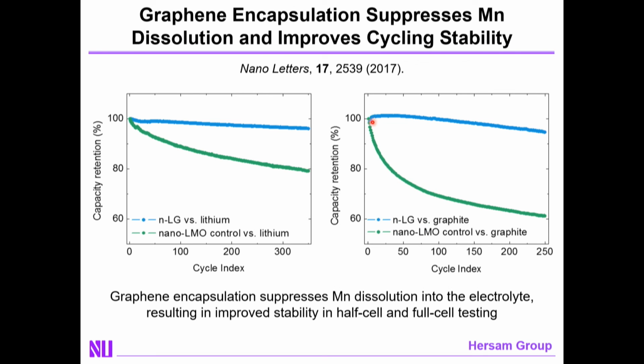In contrast, with the graphene-coated case, as you can see here, particularly in the full cell data on the right, you get much more stable cycling performance. And when you analyze how much manganese has been lost in the cathode or how much manganese has found its way to the anode, you find that it is mitigated in both cases. And as a result, you've achieved that reduction in unwanted chemistry between the electrolyte and the electrode.